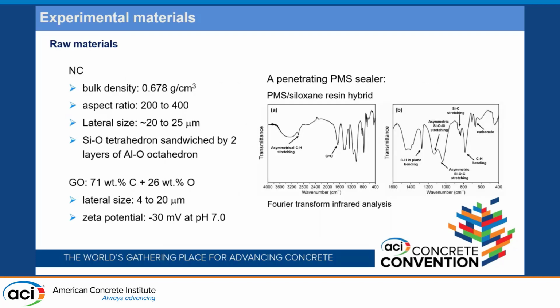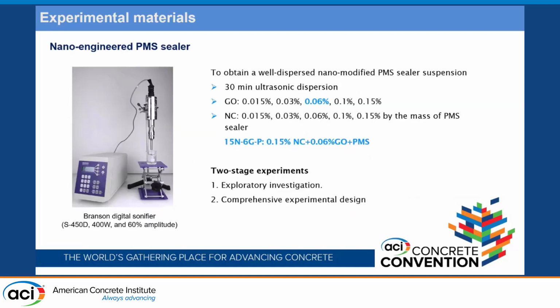This slide shows the basic information of these two nanomaterials that we used in this study. And we also investigated the chemical composition of this PMS sealer. It also contains some organic components. To guarantee the good dispersion of nanomaterials in this sealer, we use 30 minutes of ultrasonic dispersion. In this study, we use a two-stage experiment. The first one, we do some exploratory investigation and roughly determine the dosage of the two nanomaterials ranging from 0.015% to 0.15%.